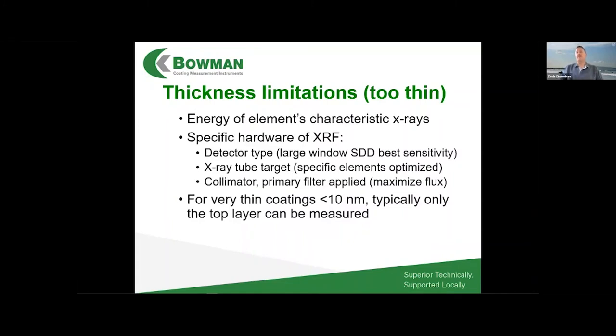On the other end, if something is getting too thin, then there's just not enough actual X-ray intensity to measure. A lot of that is going to depend on the actual hardware of the XRF, which I'll talk about in the next slides. We have a lot of the same hardware components as general XRF instruments out there. The detector type is going to be a big factor in how thin we can measure. These days for our instrumentation, a silicon drift detector with a large collection window is going to give you the best sensitivity. It's going to capture the most counts from the sample, and so that's going to give you the lowest detection limits or the thinnest measurable coating range.